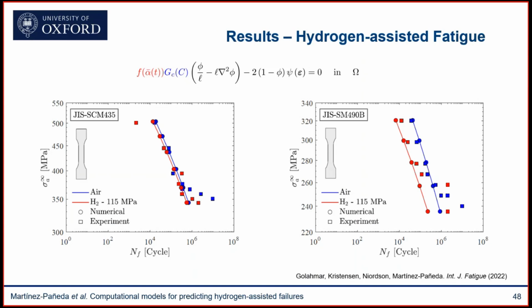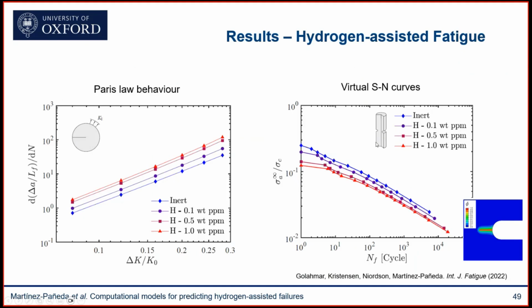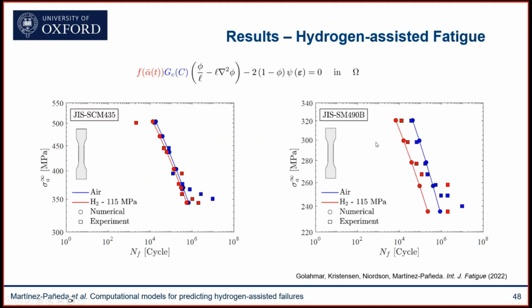Quite excitingly, we have extended this to fatigue. So in addition to having a hydrogen degradation function, you have a fatigue degradation function, a degraded fracture energy based on the number of cycles. You can see here virtual S-N curves predicted with our model, showing a relatively good agreement with experiments. And these are, by the way, cycle by cycle calculations. So this is computationally time consuming, but we have developed algorithms and methods to accelerate these calculations, and we can do now millions of cycles.